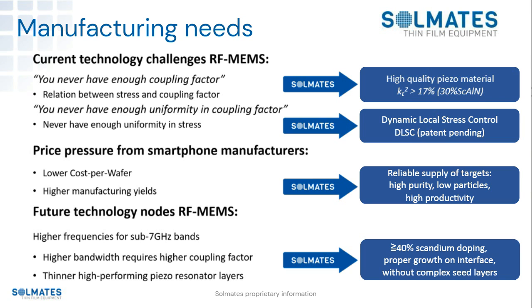Coupling factor is important, but the other thing that's really important is uniformity in coupling factor. This is well known. Stress in the layer and coupling factor are related. So therefore, what we need to do as an equipment supplier, make sure that we have uniformity in stress. There is never enough uniformity in stress. This is directly linked to yield.